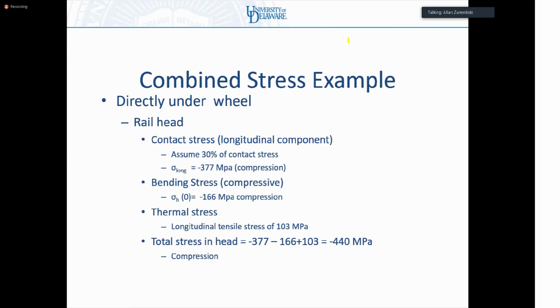So let's do an example just to show you how that works. So if my contact stress is of the order of 1200 megapascals vertically, that's what I get from my P over A. Then the longitudinal component is 0.3 times that, is 377 megapascals compression. My bending stress on the top of the railhead, we just showed you an example, is 166 megapascals compression.